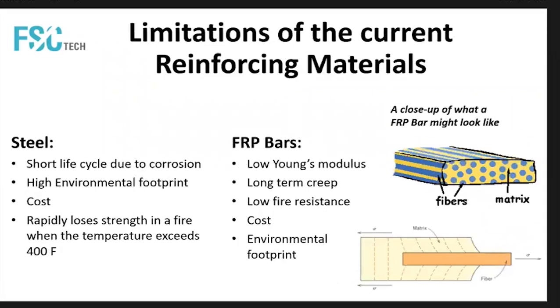The problem with the material used is about the steel. You have a short life cycle due to the corrosion. Corrosion in steel is actually the main cause of failure of any kind of reinforced concrete product. It is a material with a very high environmental footprint, about 2 kilograms of CO2 for each kilogram of steel. The cost, as we know, and it rapidly loses strength in a fire when the temperature starts to exceed a given amount, maybe a little more than 400 Fahrenheit.